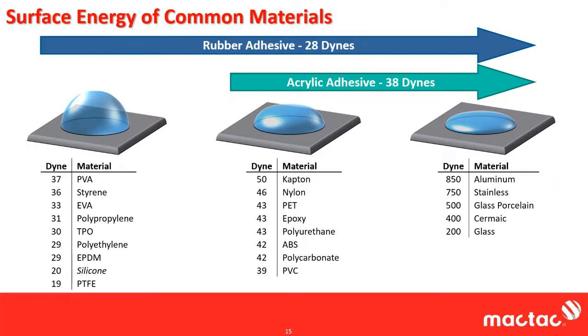Acrylics have a lot more variability. They can get as high as 45, 46 dynes, really depending on what monomers are used to make up that acrylic. I won't go into a lot of detail there, and I'll use the low end, but as you can see, acrylics just don't do very well. Straight acrylics just don't do very well on the lower surface energy materials.